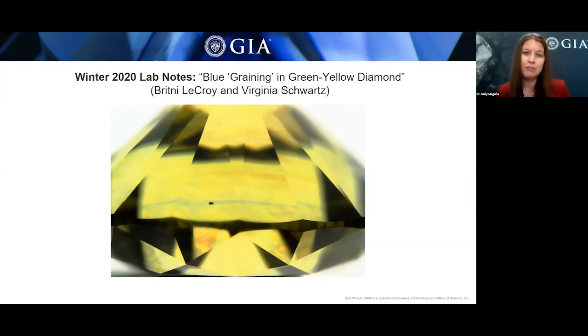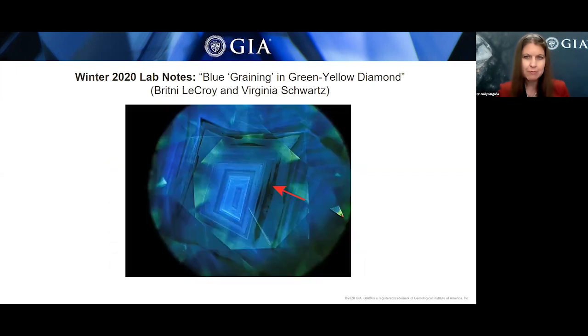Before HPHT treatment, this stone had a brown color, which with the treatment transitioned to a yellow, as well as the green luminescence, which added the greenish component. After laboratory radiation, the authors surmised that vacancies were created in higher concentrations within low nitrogen regions to create the zones of blue color.